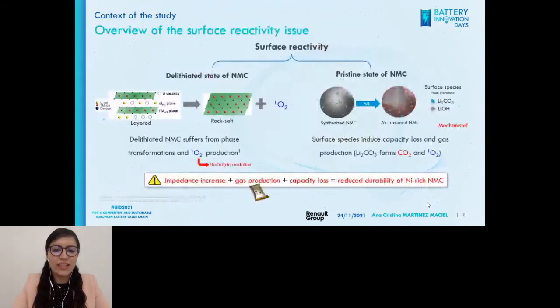So for this, next please. I show here the two sources of surface reactivity. One is the delithiated state of NMC. We know, it has been known for years, that when NMCs are in the delithiated state, meaning there is depletion of lithium in the lithium layer, these structures will tend to collapse into a rock-salt structure with production of active oxygen. The problem is that active oxygen will then oxidize the electrolyte and produce gas.